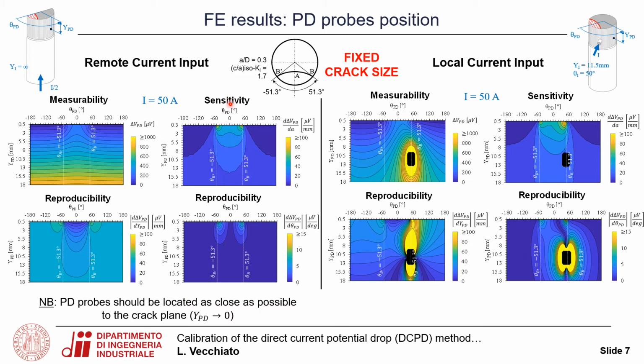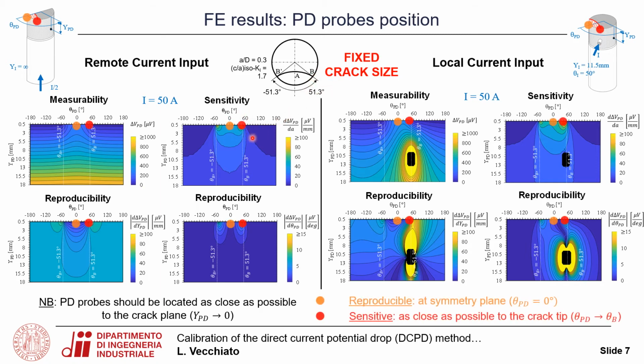Locating the potential drop probes on the symmetry plane, the reproducibility is higher, whereas locating the potential drop probes as close as possible to the crack tip, so theta_PD tending to theta_B, it is possible to obtain the highest value of the sensitivity, so that's a matter of choice.